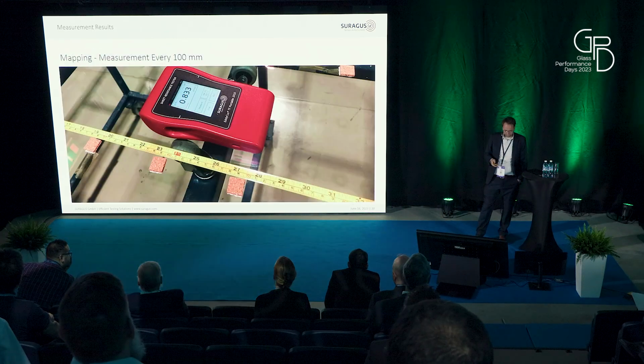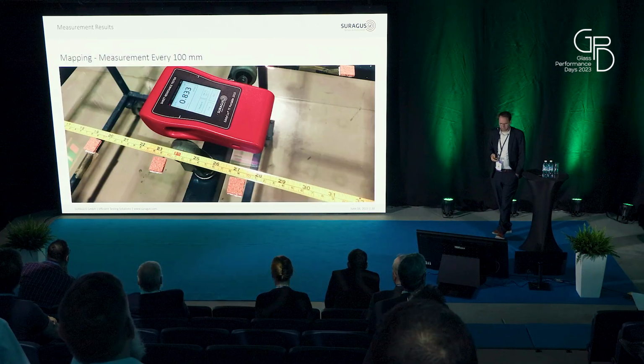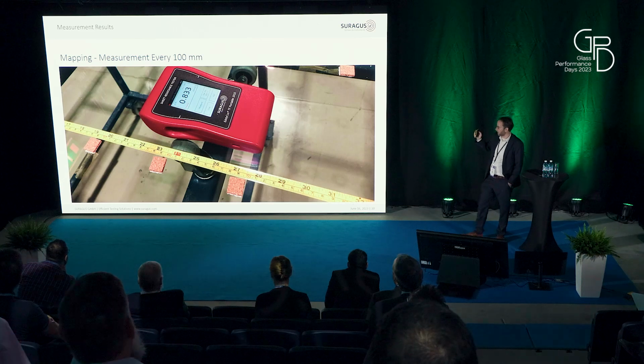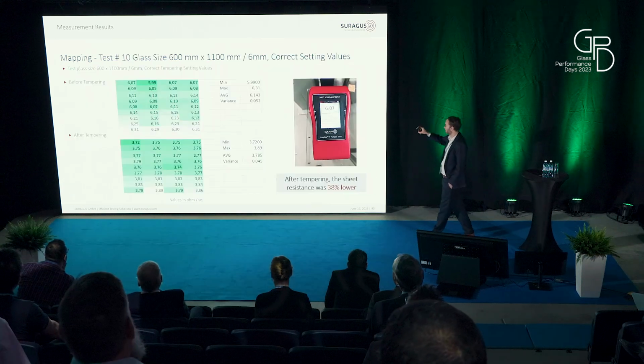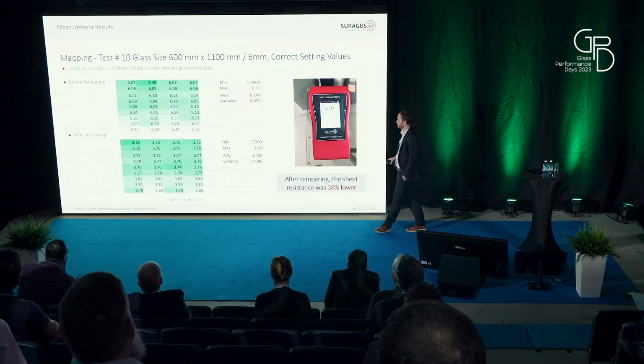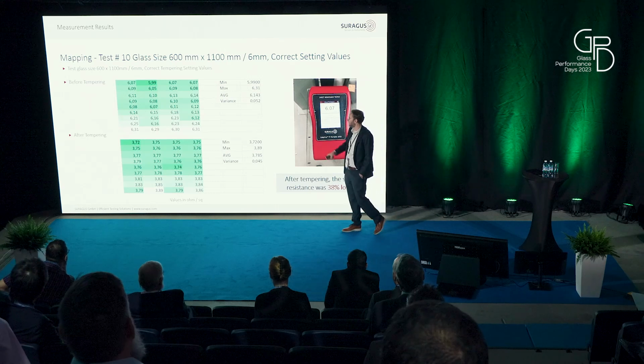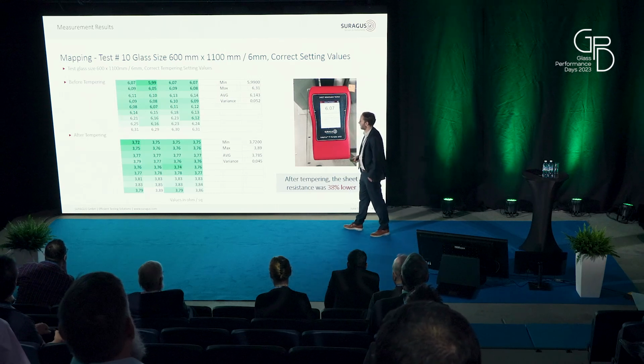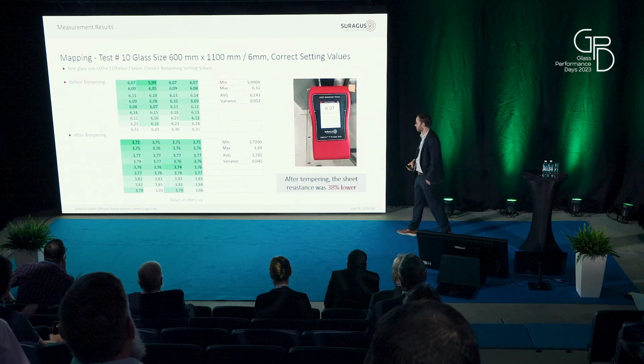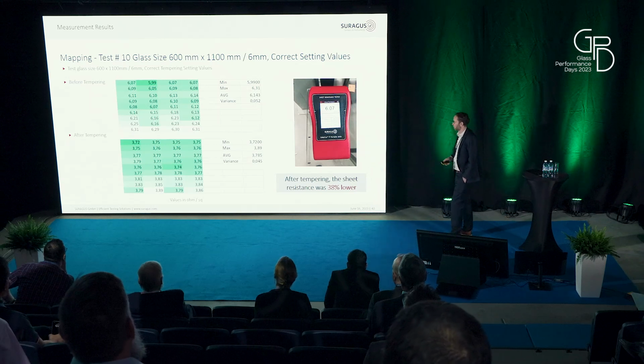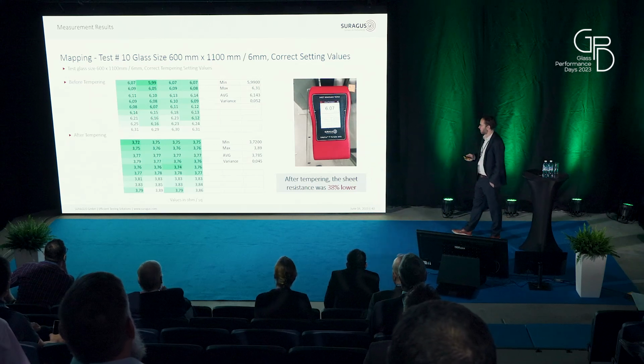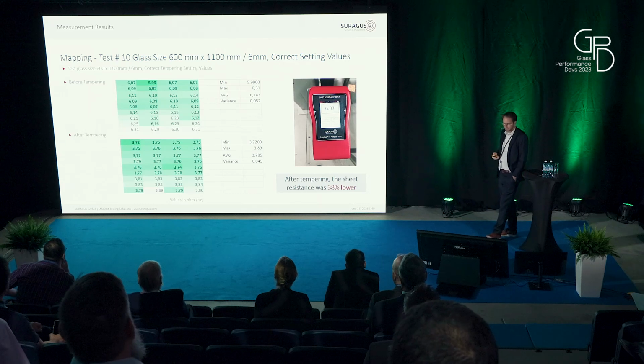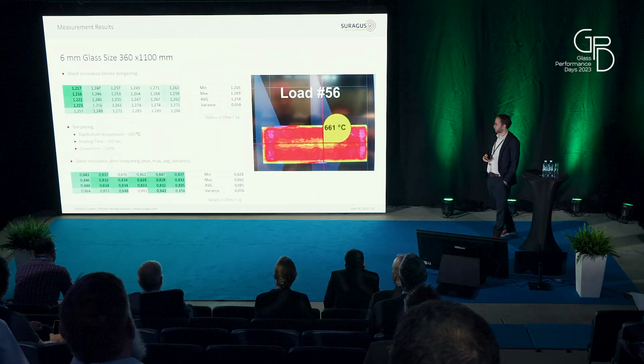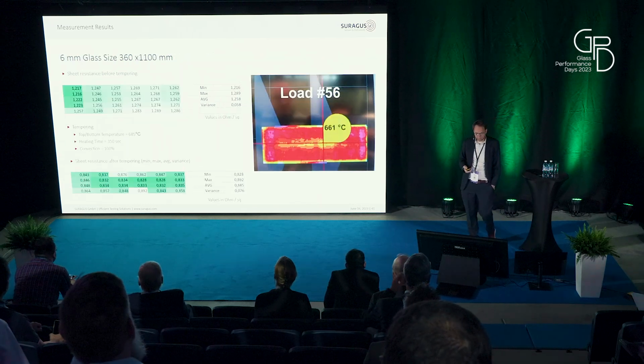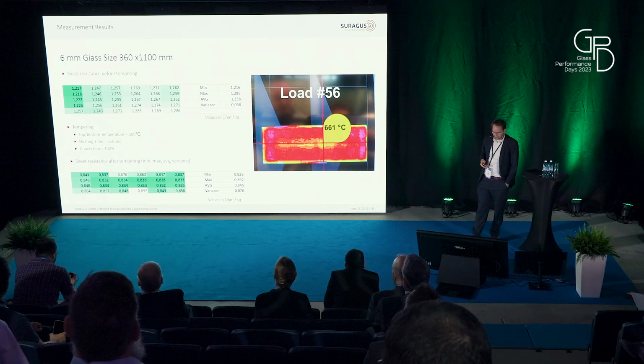We also looked at the mapping. We took manual measurements on different positions of the glass. So we have a homogeneity map in green here. Before the tempering, we have a sheet resistance of roughly 6, and afterwards 3.8. And we look at the homogeneity before and after. Sometimes there was something interesting, sometimes not, so we need more data to explore this in detail.